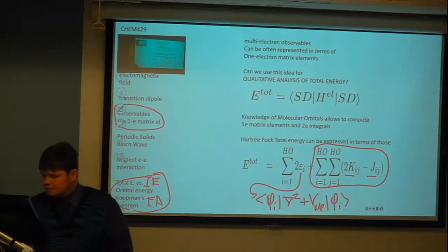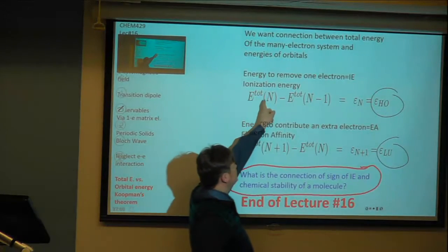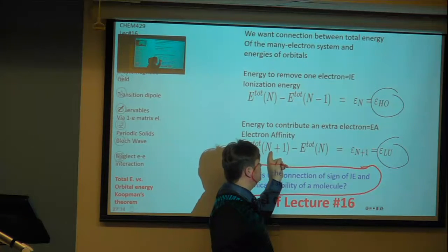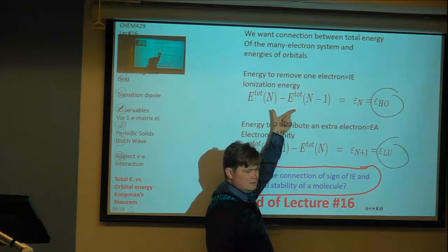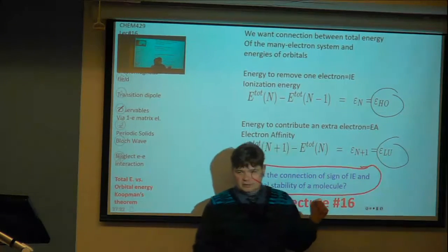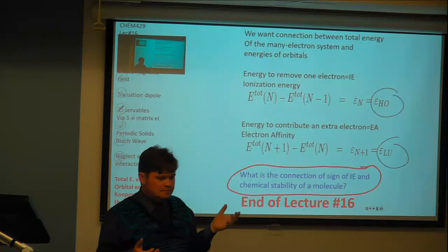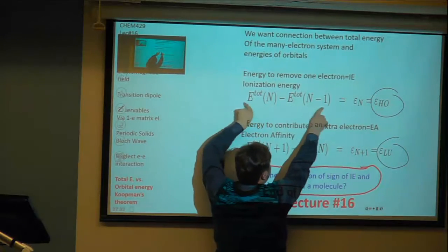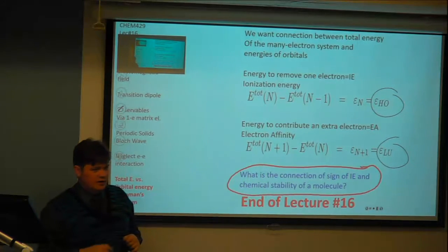And if you build a model that has a different number of electrons, one less, which will be a cation, or one more, which will be an anion, and you subtract them, then under Koopmans' approximation, it will be the energy of the HOMO or LUMO orbitals. But if you do research for publication, instead of using Koopmans' theorem, you better find total energy with different charge if you need the energy of ionization, right?